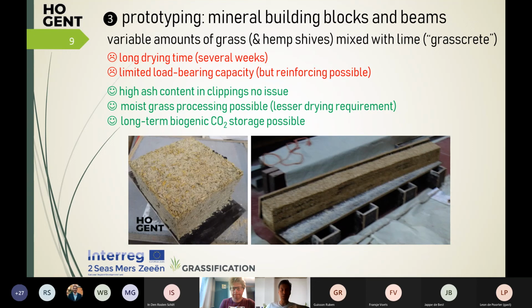Of course, this material has limited load-bearing capacity compared to concrete, especially reinforced concrete, but we could achieve some reinforcing by adding other plant-based material with tensile strength, as was the case in the beam shown on the right-hand side. This beam is about 10 by 10 centimeters and 1.5 meters long.